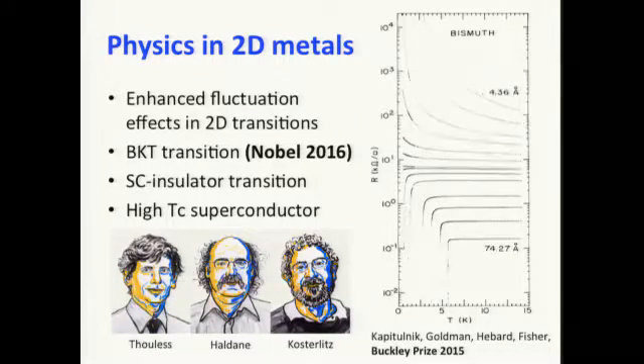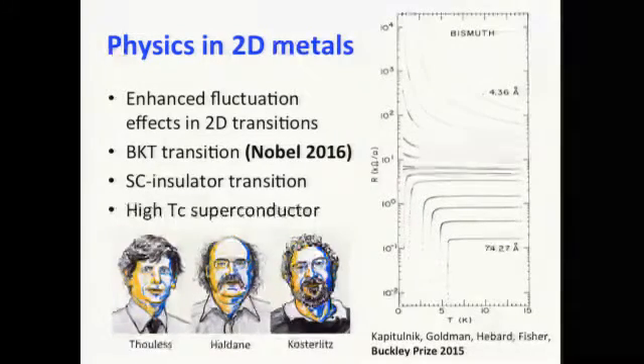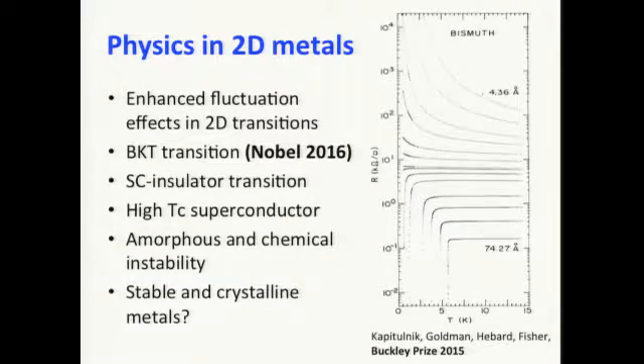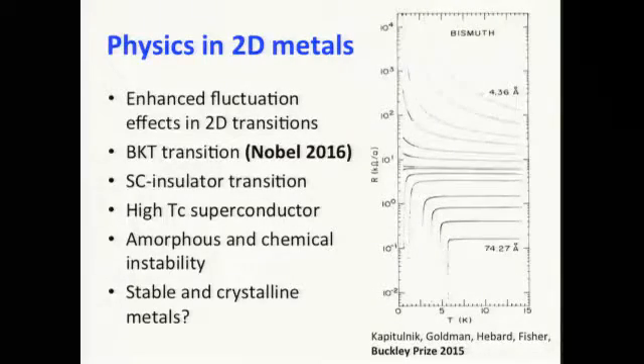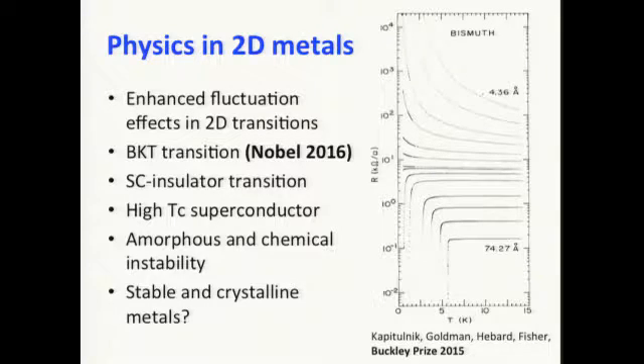But for me, this data also somewhat bugged me, because when you go to very thin materials using this method, the material becomes so disordered that it turns into an insulator. It no longer conducts electricity well. So the major problem for this kind of material is that it is an amorphous thin film, and it has lots of dangling bonds, so it's not chemically stable. So do we actually have crystalline two-dimensional metals that are chemically more stable?